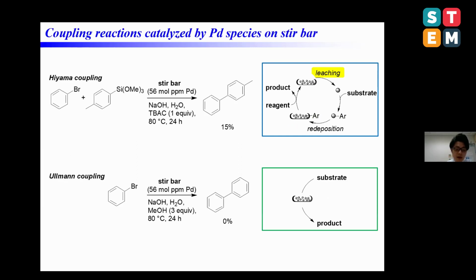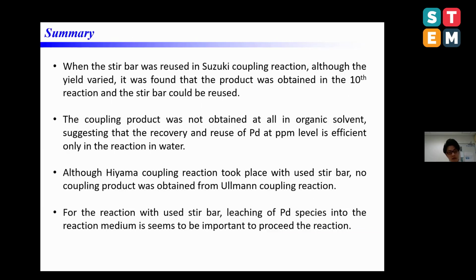Finally, we performed Hiyama coupling reaction and Ullmann coupling reaction with used stir bar. Although the coupling product was obtained in Hiyama coupling reaction, no reaction was confirmed in Ullmann coupling reaction. Considering Ullmann coupling reaction takes place on the catalyst surface, it is consistent with this result. In summary, when the stir bar was reused in Suzuki coupling reaction, although the yield varied, it was found that the product was obtained in the 10th reaction and the stir bar could be reused.